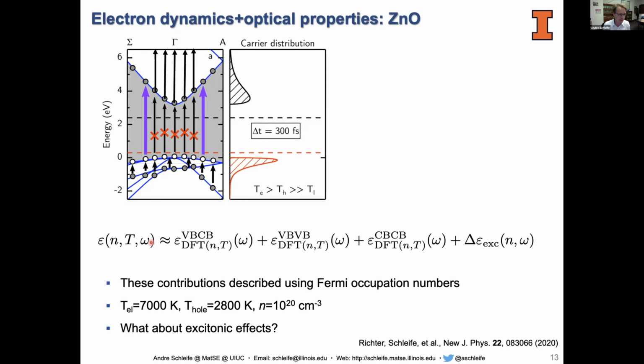So the way we approximated this now in our framework is we treated most of these effects, and that's again a limitation of the current framework, in DFT. So all valence-conduction band transitions as a function of carrier concentration and temperature we treated within DFT. We also treated valence-valence and conduction band transitions within DFT. Mostly because in the Bethe-Salpeter approach, we currently have an implementation that can approximately account for free electrons, but not for temperature. So I'll tell you that on the next slide.